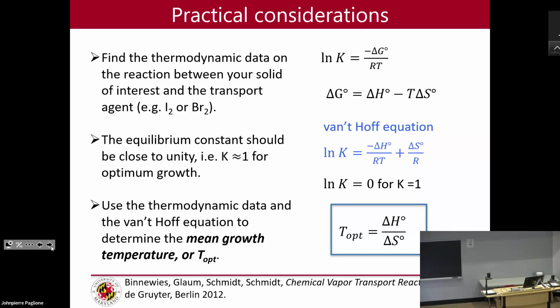You don't want to have a huge temperature gradient, because if you do that, then you have transport that's too fast, right? And if it's too fast, you'll get your product, but you'll get a polycrystalline product. So you need to slow it down, have a nice temperature gradient that is very gradual and not so steep, so that you can optimize larger crystal growth.